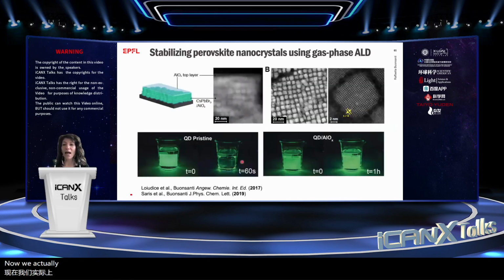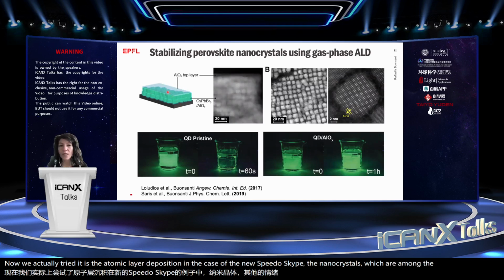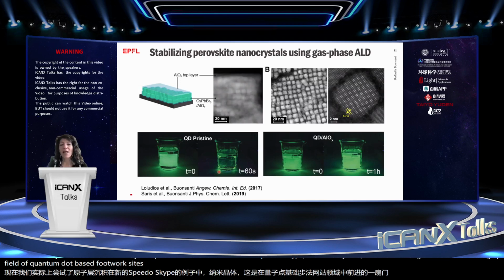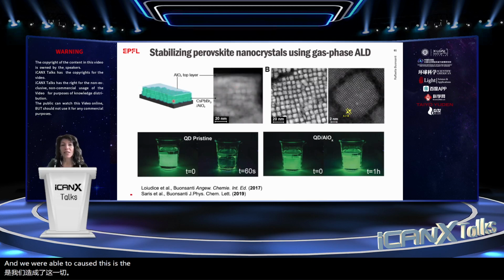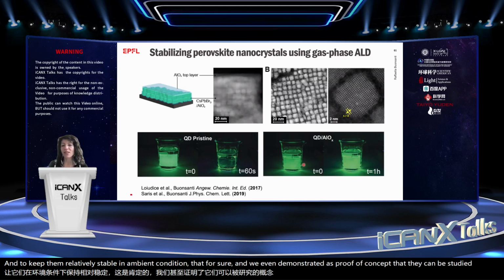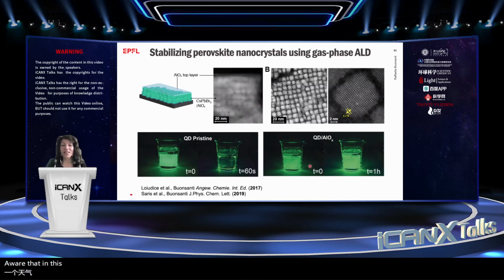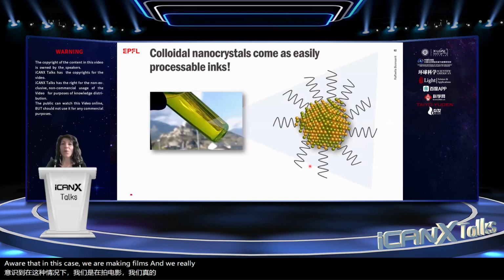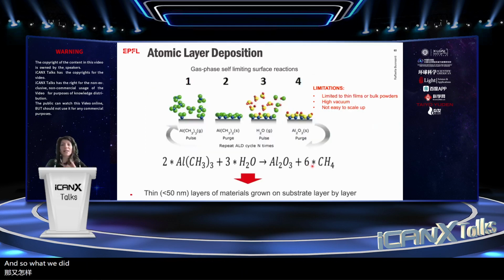Now, we actually tried this atomic layer deposition in the case of these perovskite nanocrystals, which are among those advancing the field of quantum dot-based photovoltaics. And we were able to coat these nanocrystals with a layer of aluminum oxide and to keep them relatively stable in ambient conditions. We even demonstrated, as proof of concept, that they can be stabilized in water. However, in this case, we are making films, and we really wanted to keep our quantum dots as processable inks.